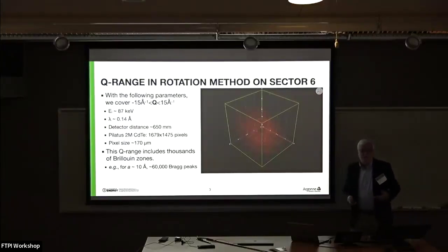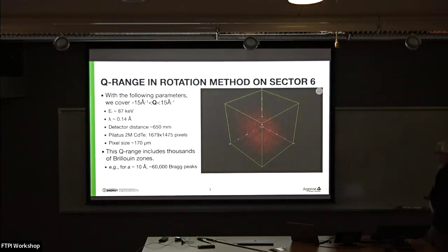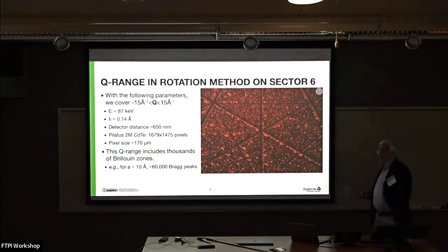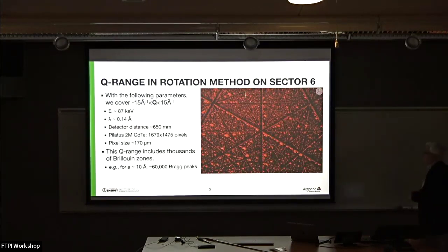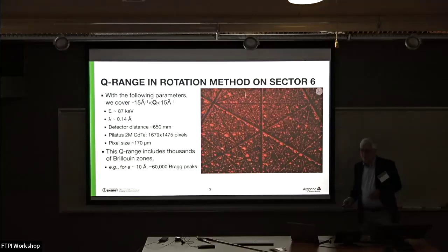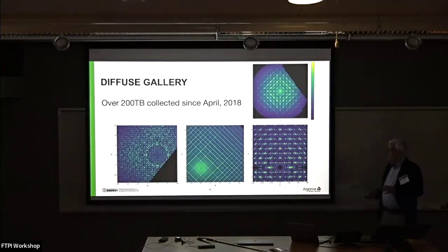And to give you a flavor of what that volume involves, this is actual scattering from measurements. We use 87 keV X-rays at the Advanced Photon Source. That means we're measuring over about 15 inverse angstroms in all directions. And that means that's an awful lot of Bragg peaks. It's thousands of Brillouin zones, sometimes tens of thousands. And we're measuring it with a fine HKL mesh in all of those zones. So this is a large amount of data. A lot of it's very pretty. It all looks extremely different from one another.